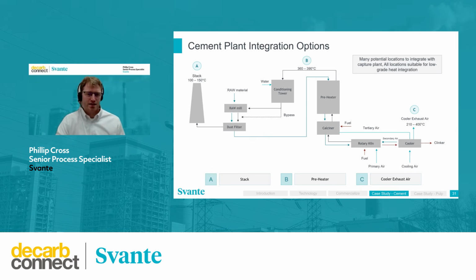So the last area is at the clinker cooler air. The advantage here is that the hot clinker cooler air can be sufficient for generating some low pressure steam for CO2 capture, or can be used to preheat the raw mill. Again, one of the cons here is high dust loading.